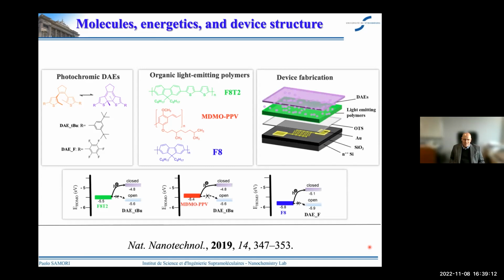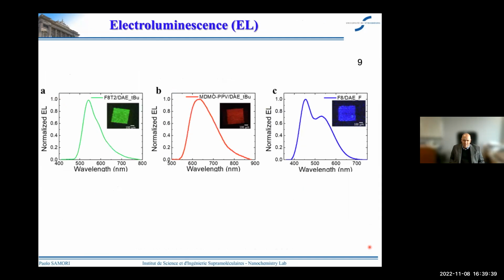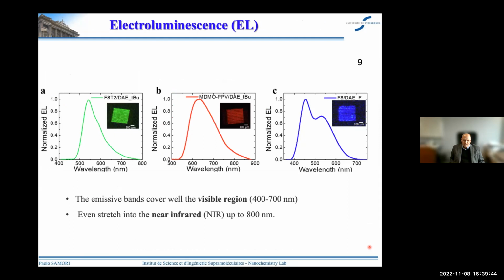Now, more precisely, we can use the diarylethene with tert-butyl units for trapping and detrapping the hole transport, both for the green and the red emitter. But instead, for the blue emitter, we were forced to use another type of diarylethene, that is the fluorinated one. This is all based on the energy level of the semiconductor. Now, the blends are highly luminescent, so they cover very well the spectra in the visible range, and they even stretch in the near infrared up to 800 nanometers.